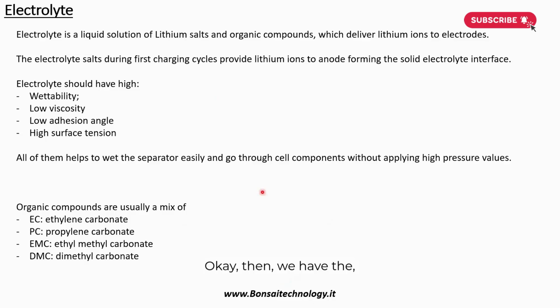Okay, then we have the electrolyte. As mentioned before, the electrolyte is a mix of lithium salts and organic compounds, okay? The lithium salts dissolve in the organic compounds, and dissolving releases the lithium ions that are able to flow through the separator, okay? The electrolytes have some KPIs as well. One is the wettability: low viscosity, low adhesion angle, and high surface tension. All these KPIs allow the electrolyte to be soaked by the separator. Okay, so the separator must be able to be wet by the electrolyte.